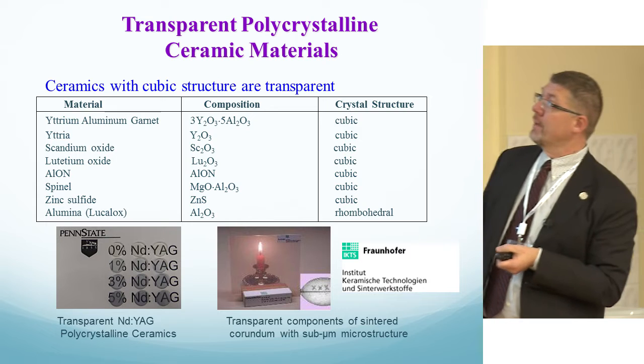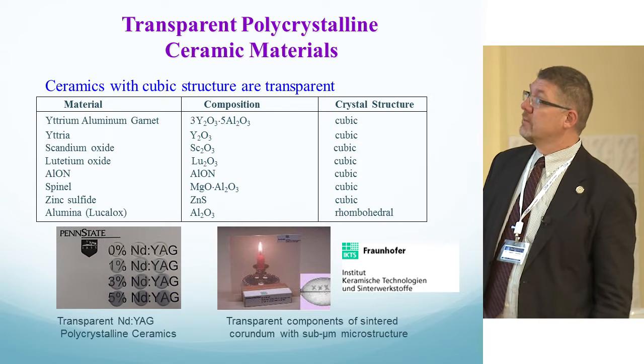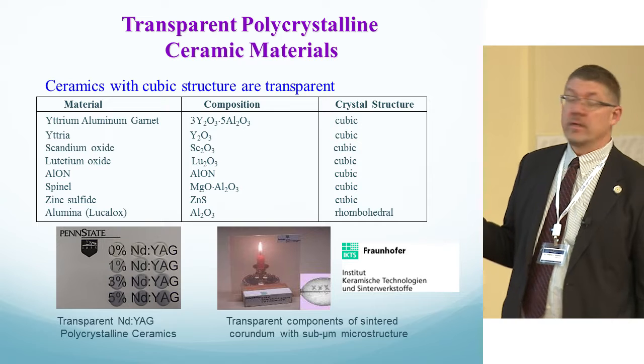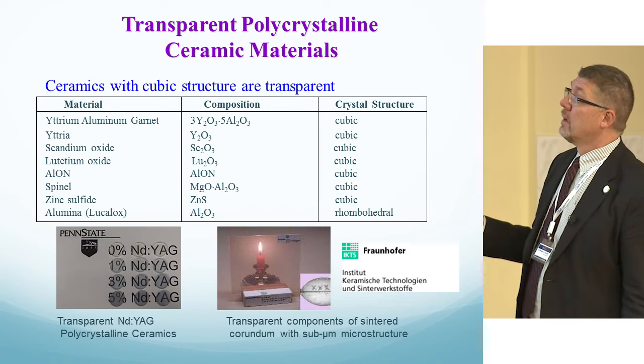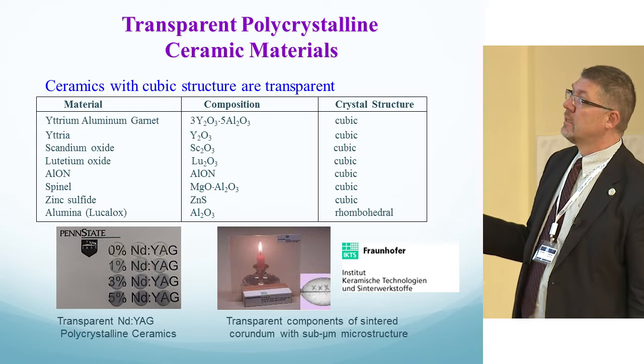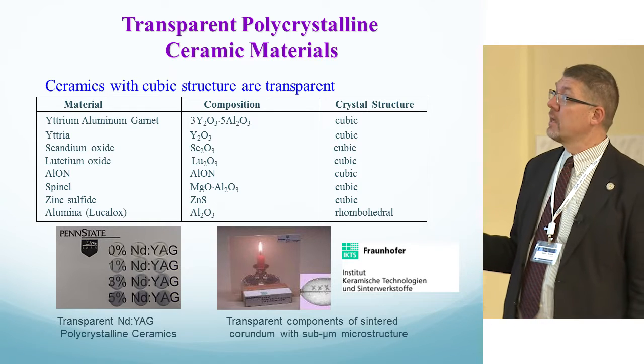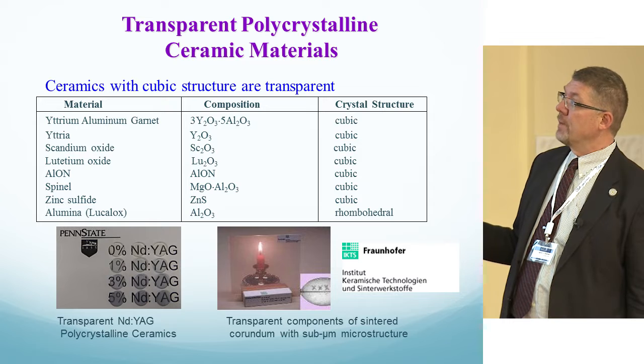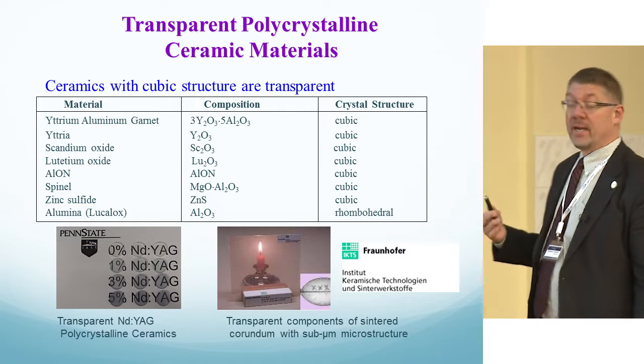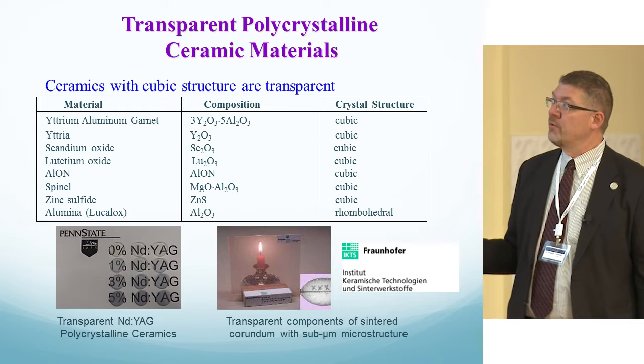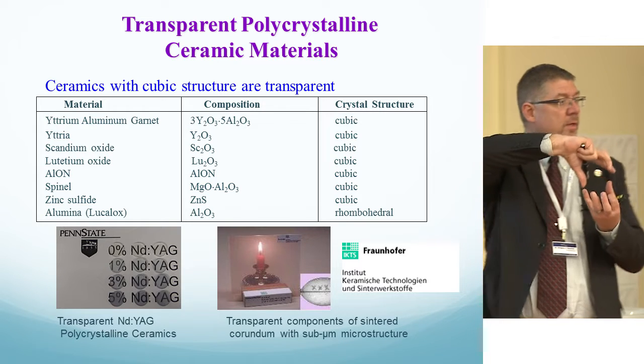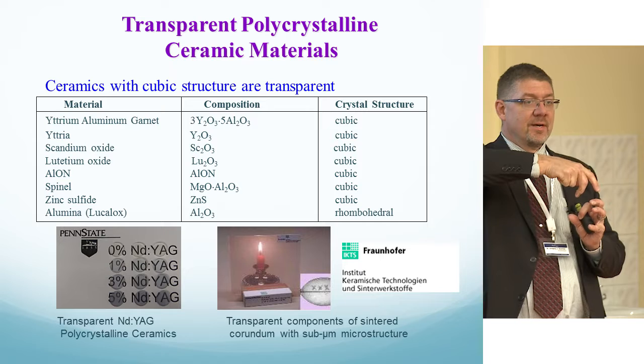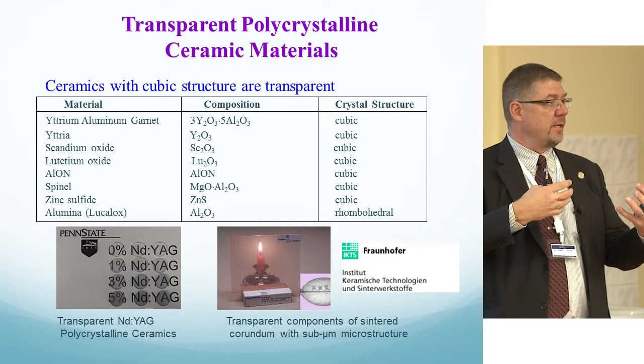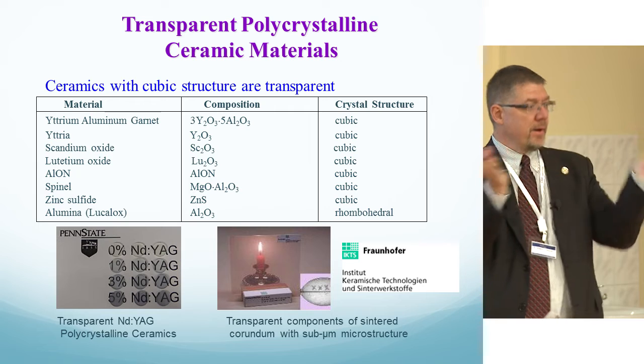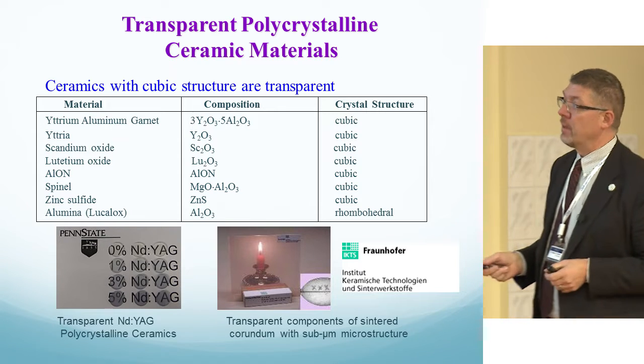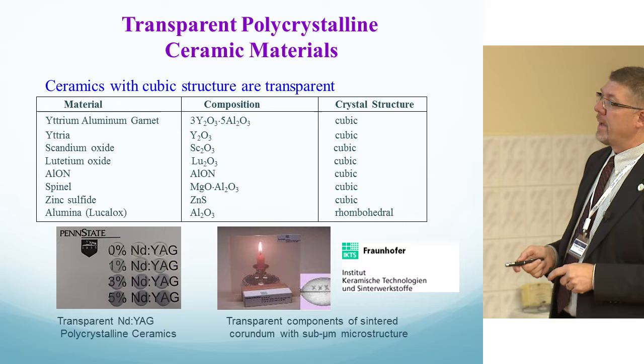Some of the materials that are cubic that have been made transparent: YAG that we've talked about, yttria, scandia, lutetia, all the sesquioxides, aluminum oxynitride (ALON), spinel, magnesium oxide, aluminum oxide combination, zinc sulfide, and then alumina (Lucalox) has also been made. It is rhombohedral, but the primary driver for the alumina is for the outside of the sodium vapor lamps. They need a very high temperature material to dissipate the heat, but it doesn't have to be laser quality. If it's transparent and can get the sodium vapor light out, then that's good enough for them, and they can make it in a very inexpensive format.